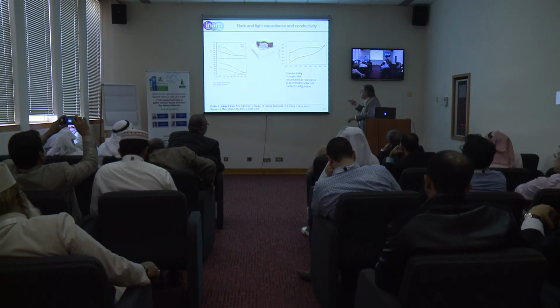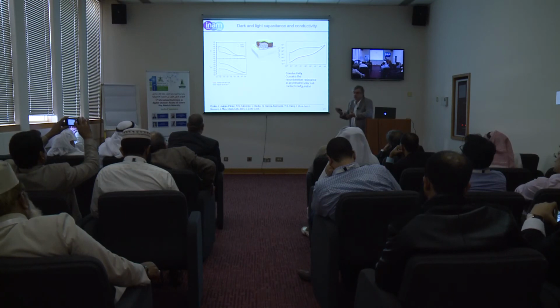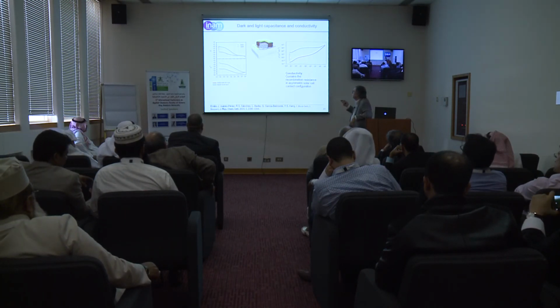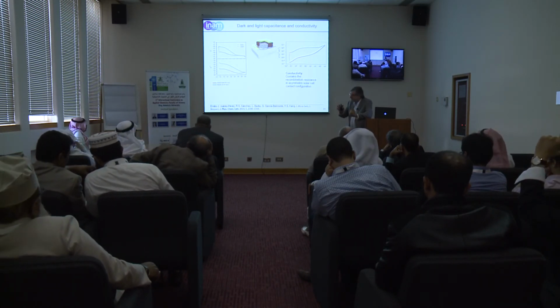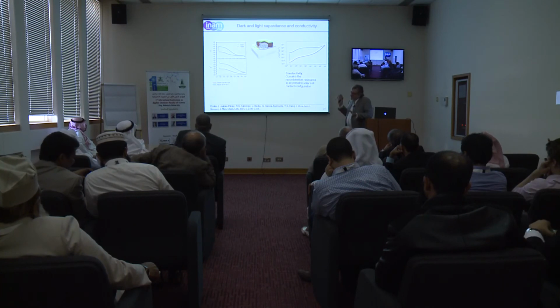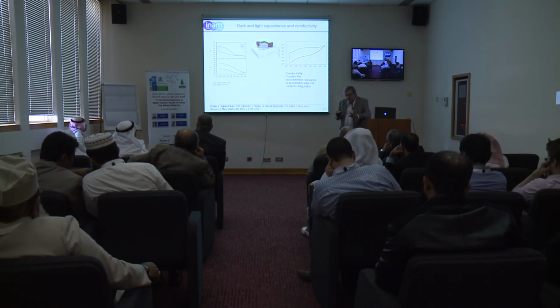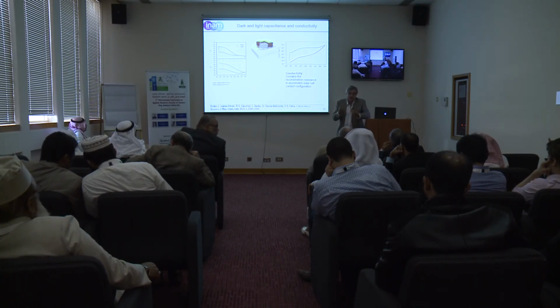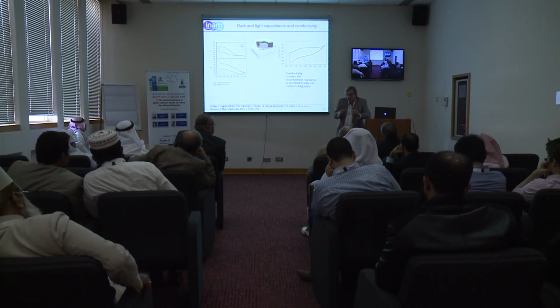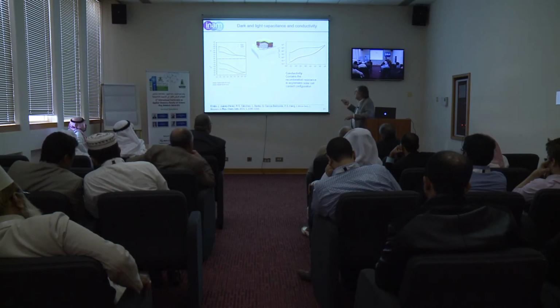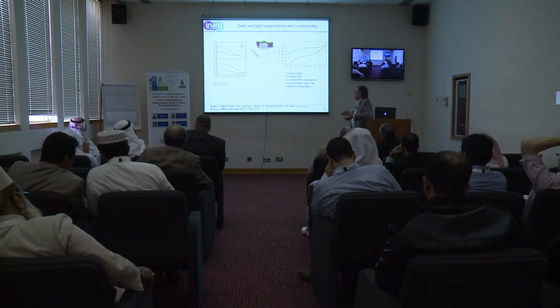At the same time, conductivity will increase. Well, this is natural, because you are putting carriers in with light. So we expect the conductivity to increase. This is not really conductivity at low frequency, as this is not a symmetric sample. So this is a plot of conductivity, but in a solar cell, the DC current is not conductivity, it's recombination, because the only thing you can have when you come to DC, when you pass steady state current, is a recombination current, always, because it's a diode. But anyway, it's affected by conductivity, and it increases a lot.